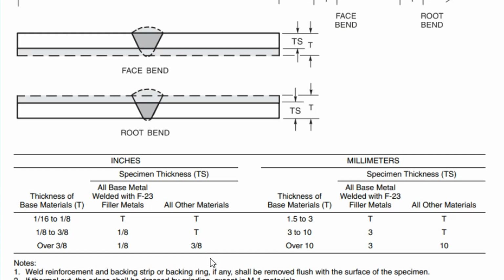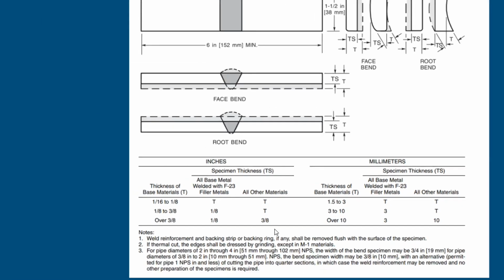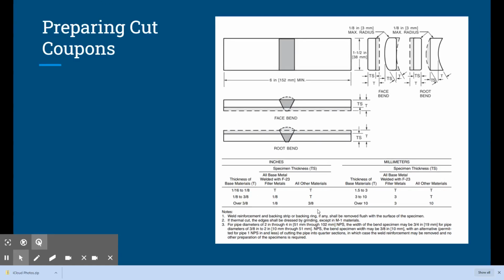Now, that's important to look at because a lot of people will do this part at their discretion. They'll grind until the undercut comes out. Now, you remember, you're allowed a 32nd of an inch of undercut. So if you grind your coupons down until there's no undercut, they're actually a 32nd of an inch undersized. Again, I don't see anywhere in here what the tolerance is for that. So let's say there was a 1/16 tolerance for how thick your coupons are, then that 32nd of an inch would be fine. I like to get them fairly uniform. If there's some undercut there, as long as it's less than a 32nd of an inch, I'll still leave it in there. If it's super minor and it's almost gone after we're done grinding off the reinforcement, then I will maybe take the rest of it off just to clean it up. But leaving the undercut in there isn't a big deal. You can do that. We're shooting for that 3/8 of an inch on our material thickness.